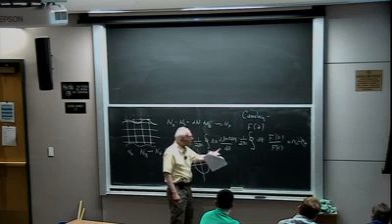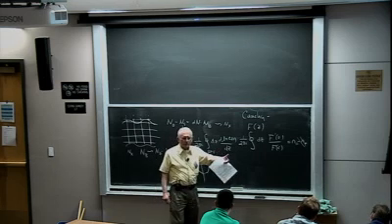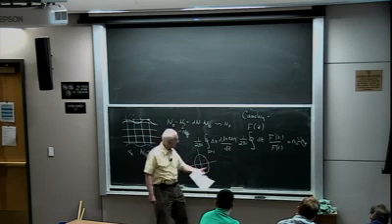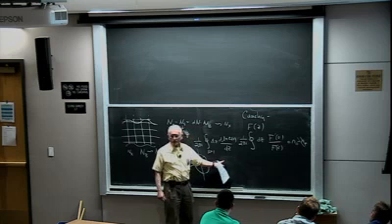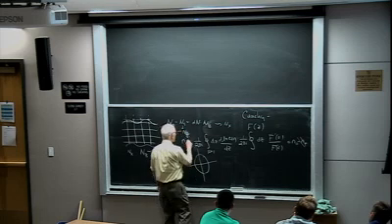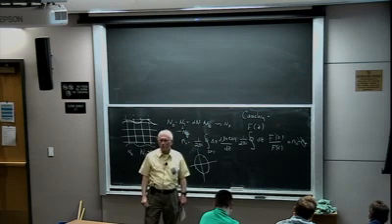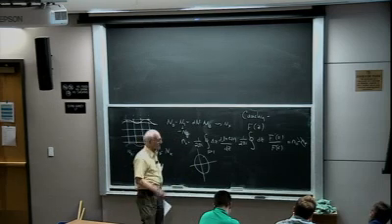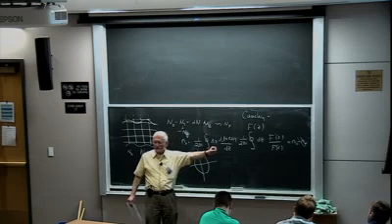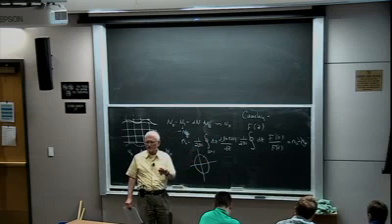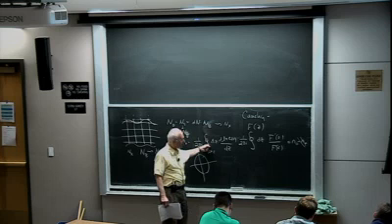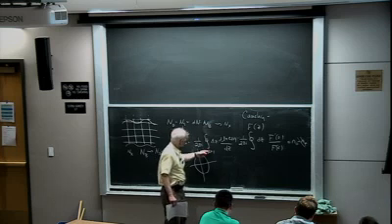I just use this as a number. So for our case, if C1 is less than C2, then we have a zero in there. If C1 is greater than C2, there's a zero that sits out here, which we don't count. So by looking at this topological number, for our case, we either get 0 or 1. If I get 0, that corresponds to having a 0 mode on the other side. And if I get 1, I have a 0 mode on the left side. So this tells us that by doing this topological integral, if you wish, which is this integral,